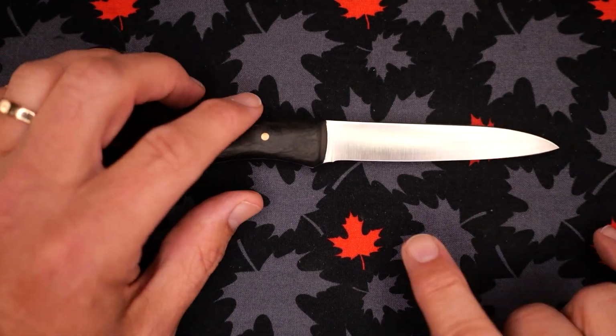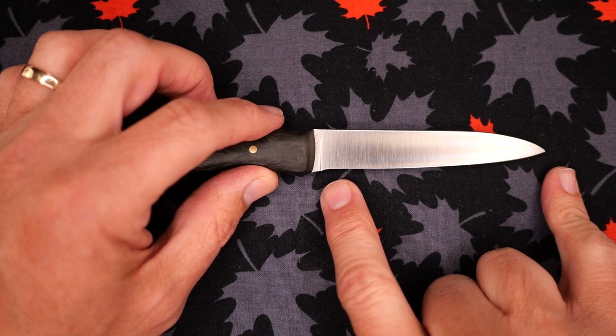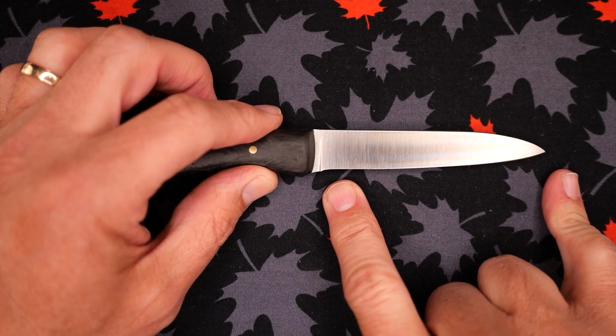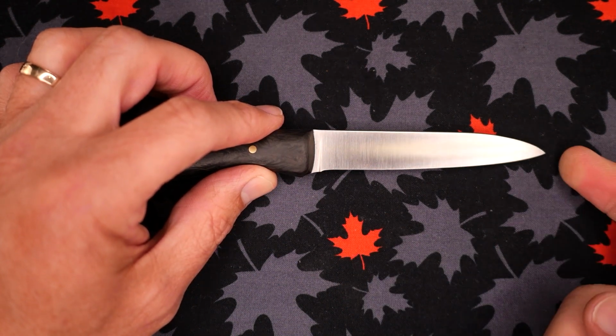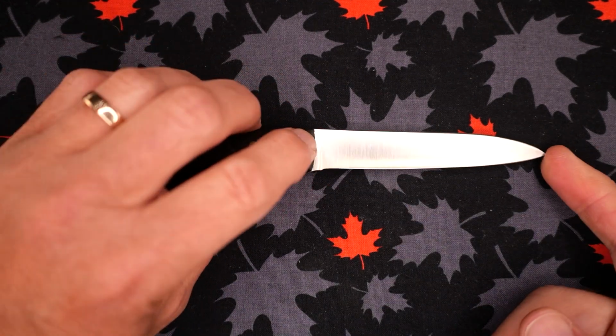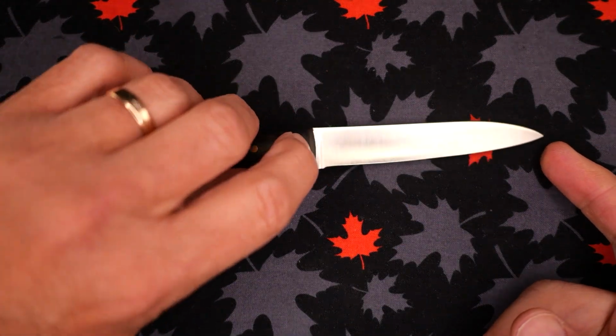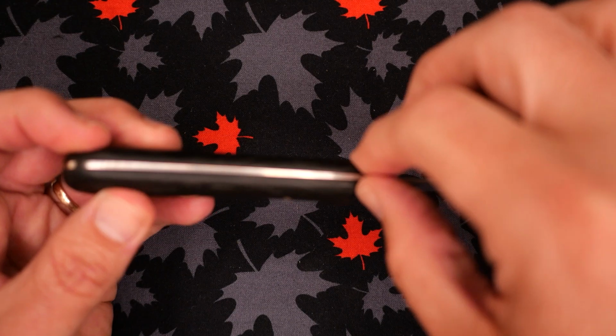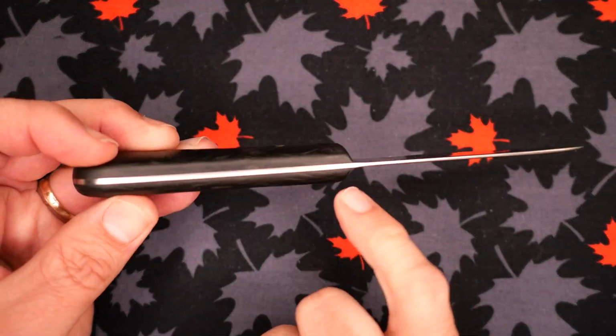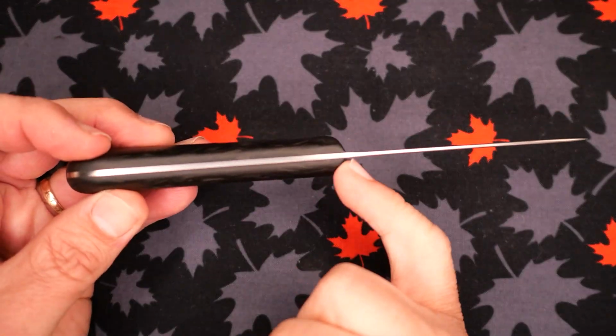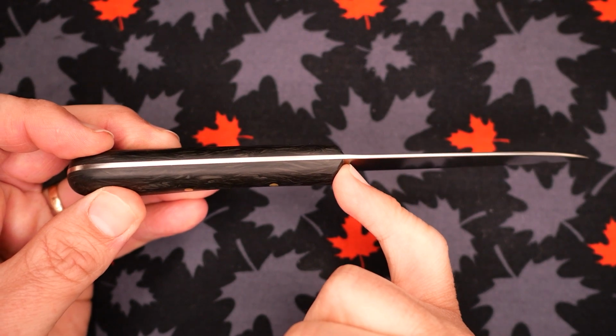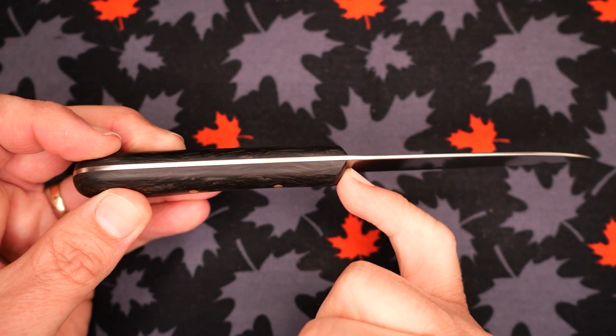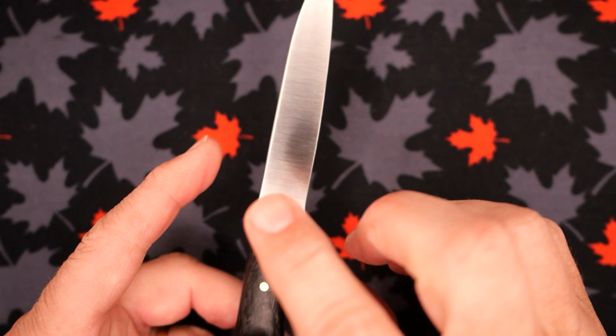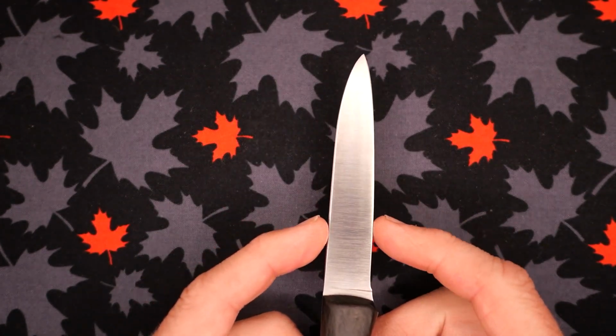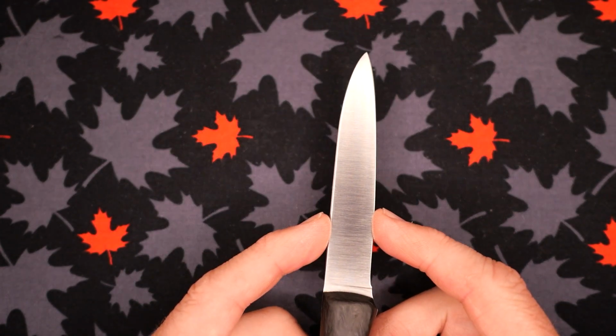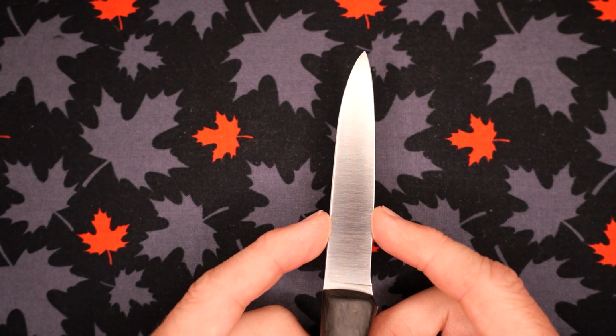The other numbers, cutting edge, 87 millimeters roughly. That's almost 3.5 inches. Blade length, tip to the closest spot on the handle, 90 millimeters, just over 3.5 inches. The thickness of this blade steel over here at the thickest spot, at the spine, 1.53 millimeters, which is 60 thousandths of an inch. The blade depth this way, it's widest right about there, and that is 16 millimeters, 0.63 of an inch.